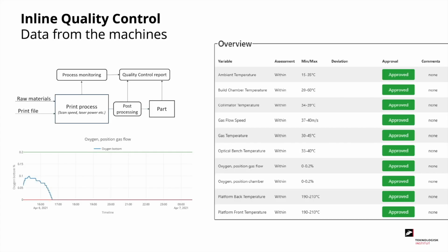Data from the machines can also be used for inline quality control. All modern systems have a lot of sensors. You see an example of that to the right, where all kinds of sensors are listed. These are both temperature sensors, but also sensors for the gas flow and the oxygen level. For instance, oxygen has to be below 0.2 during the build job, because too high a degree of oxygen will result in a lower quality of part.